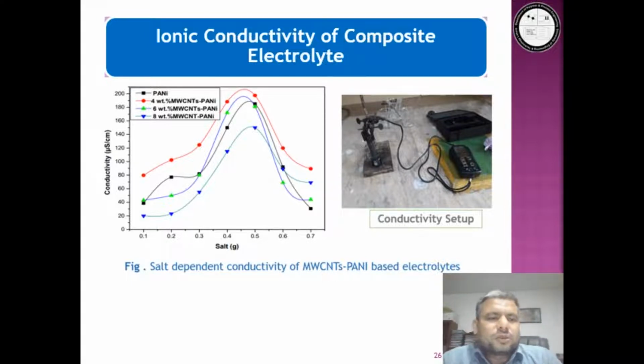So in order to improve the morphology or structure, aniline is in situ polymerized with multi-wall carbon nanotubes. The one-dimensional structure of multi-wall carbon nanotubes may fill the empty spaces and provide an effective path for the movement of electrons. Thus, 4-weight% composite-based electrolytes show higher conductivity value compared to other electrolytes. But conductivity falls to a low value with the further increase of CNT contents in the composites. It may be due to agglomerates formation at higher CNT contents.